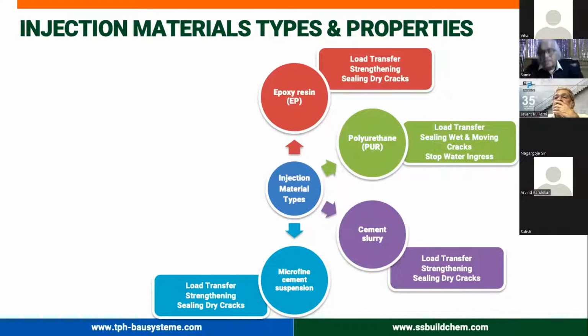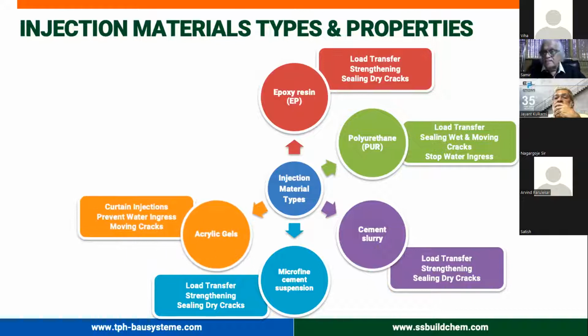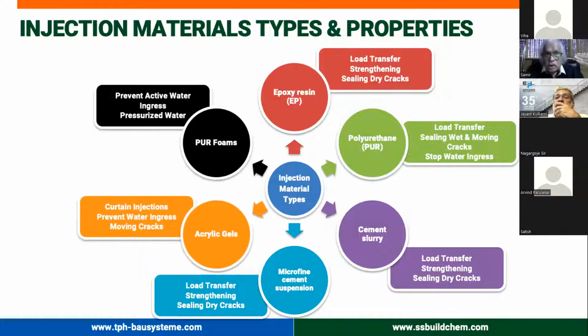Epoxies are not compatible. Many people will tell you when you make anti-carbonation coating, my epoxies are available in ultraviolet. Yes, epoxies are available with ultraviolet radiation resistance. But are you using it? A micaceous red iron oxide primer to be applied on concrete, for what? It is a steel bridge specification. Steel and concrete are two different things. So depending on the type, we have more than 20 to 30.